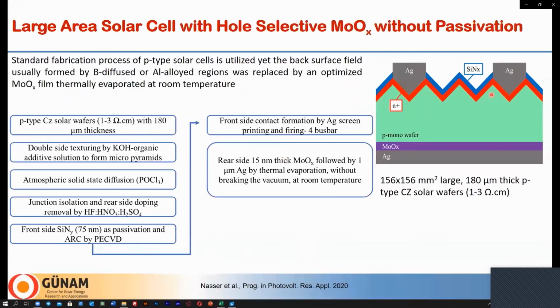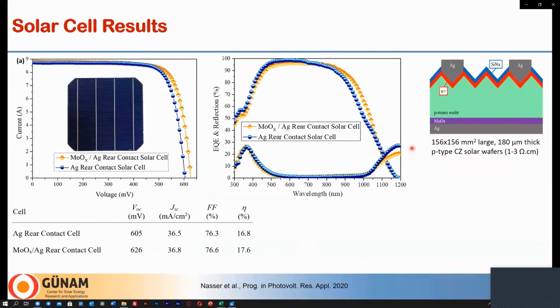We also prepared some solar cells without molybdenum oxide as reference. And these are the IV curves of the solar cell with molybdenum oxide and silver as rear side passivating dopant-free contact, and then the reference cell. We have higher efficiency with molybdenum oxide with a reasonable fill factor. The high fill factor here is evidence of effective hole transport through molybdenum oxide. However, the overall fill factor is still low, and it may be limited not only by the back side, but also by the front side doping and metallization recipe.